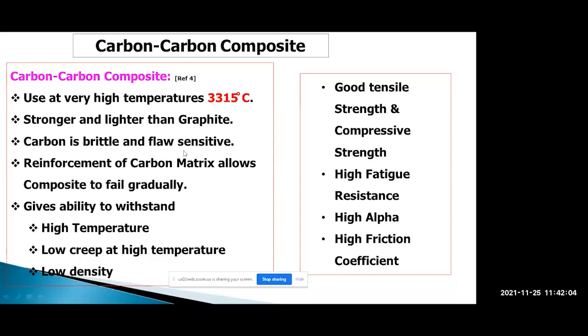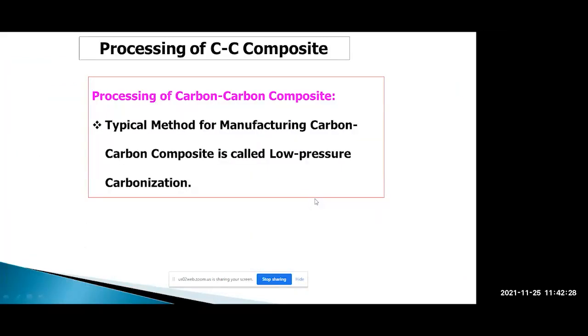Carbon is brittle and flaw sensitive. So reinforcing the carbon matrix allows the composite to fail gradually. There also fracture toughness will be very low, so we have to reinforce the carbon composites. This gives the ability to withstand high temperature, low creep at high temperature, and very low density. They have good tensile and compressive strength, high fatigue strength, and a high frictional coefficient. So brake discs are generally made from them.